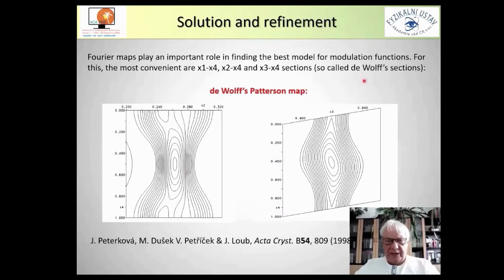Sections can also be used to make analysis of the Patterson map. Then we can take one particular peak, which follows from the average structure, and make a Patterson map for this specific position. Then from the broadening of this peak in three different directions, we can conclude about the position modulation of the heavy atom. This method was used in our paper a long time ago, and it's a little bit difficult method, but it's a nice presentation of modulation in a crystal.